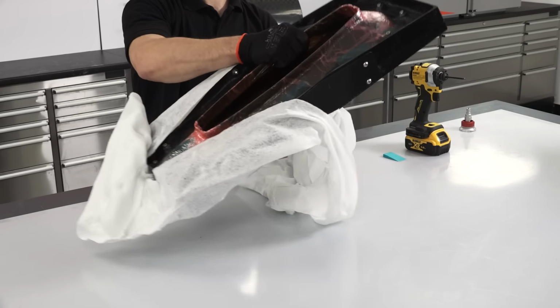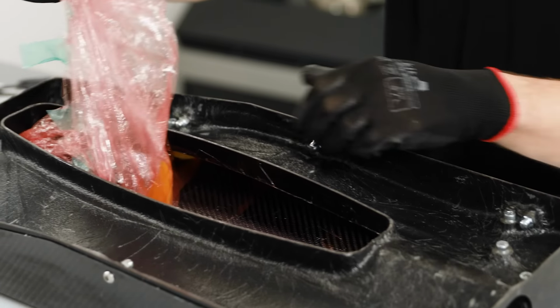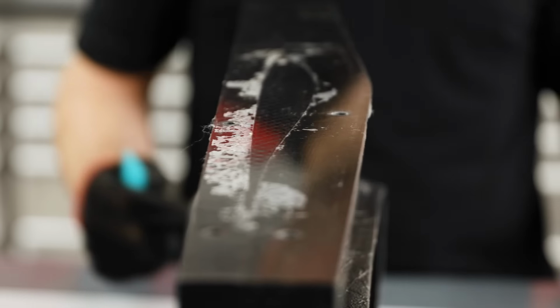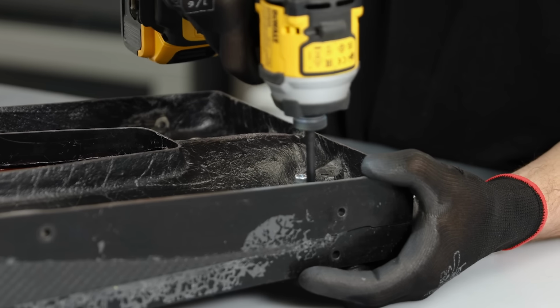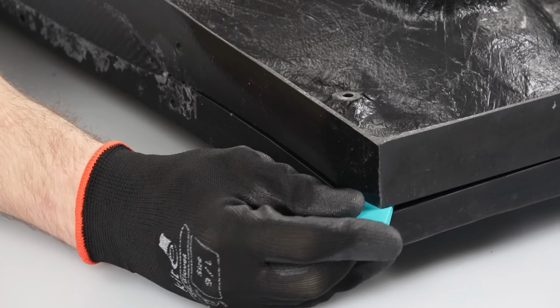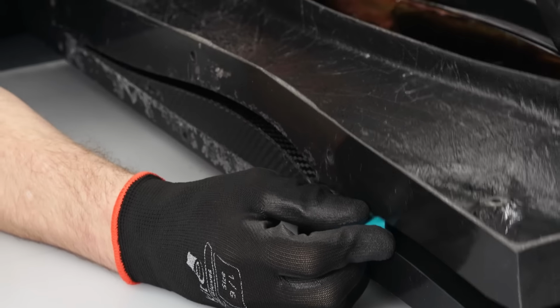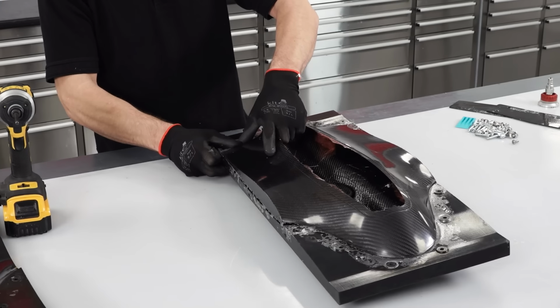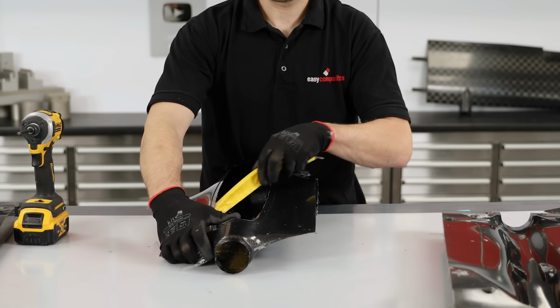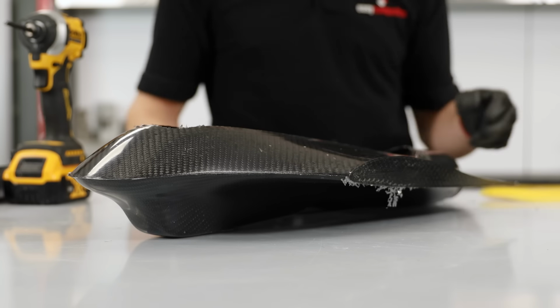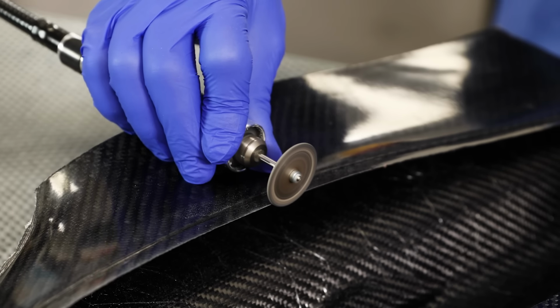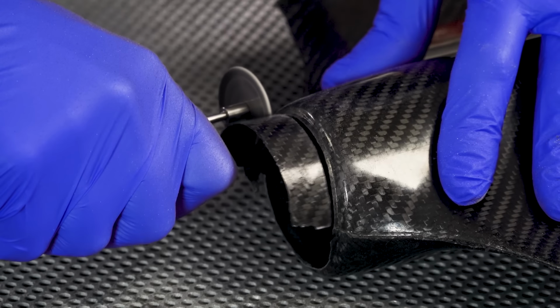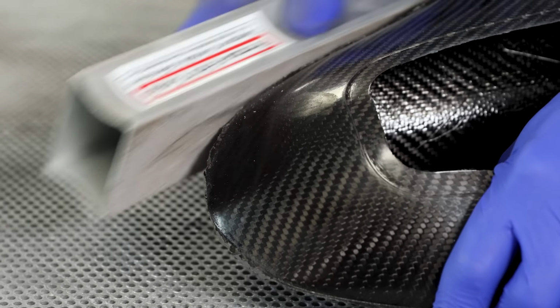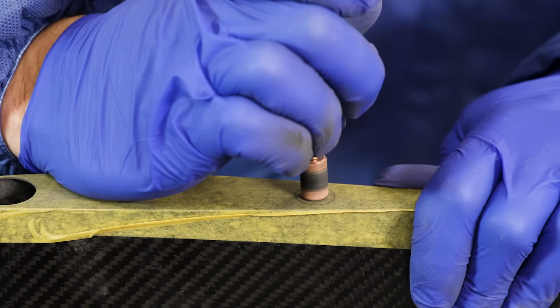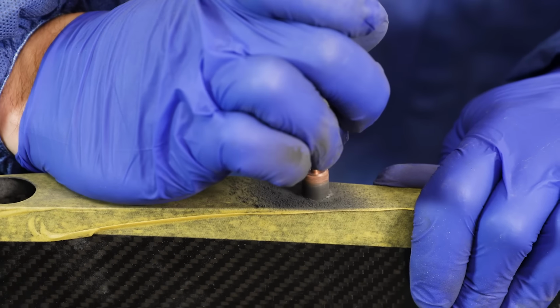Now we're on to my favourite part of any composite project, the demould. As soon as the side plates are removed, I can already see that the intensifiers have done a great job, leaving crisp, void-free corners. The part then pops out with no problems, and I can remove my silicone intensifiers. This fuselage is already looking great. I can now remove the flash and get the edges trimmed back with a Permagrit wheel and sanding block. Then it's a bit more Permagrit action to trim the holes for the spar tubes.